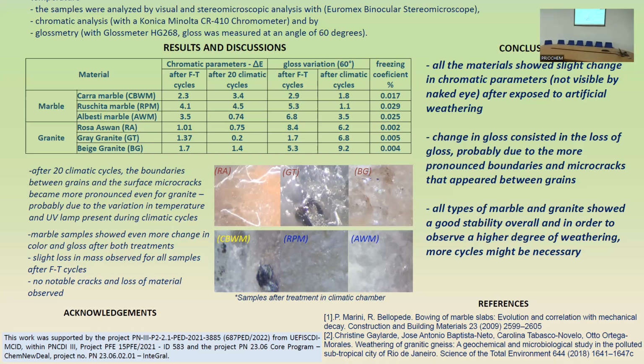Porosity of all the materials was very, very small. It can be seen in the freezing coefficient that we measured after freeze-thaw cycles, that the samples did not change much in their porosity and internal structure. They are not porous materials that absorb a high amount of water and suffer a high degree of effects after freeze-thaw, such as mortar and concrete, which are porous and will suffer considerable effects. Thank you. You're welcome.